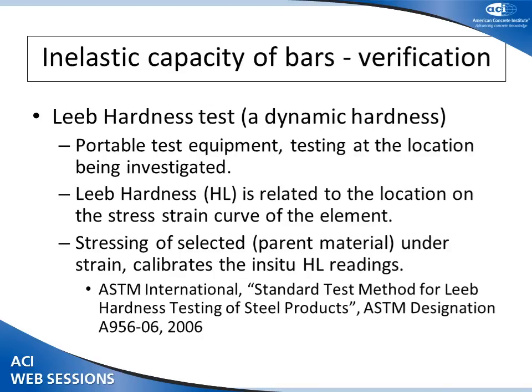The way we're doing this is with the Leeb Hardness test. It's a dynamic test, it's portable, it's a little device, it's calibrated. We calibrate it against the stress strain curves of the parent materials. We take bars from different parts of the structures where the bars have not been highly stressed. And this is based on an ASTM A956 standard. And we can relate those Leeb Hardness tests to where the bar is on that curve. And then we can judge how much deformation capacity that building or that element has remaining.